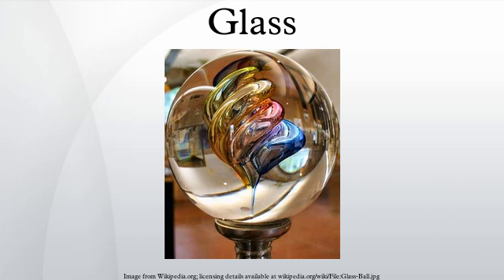The reason for the observation is that in the past, when panes of glass were commonly made by glass blowers, the technique used was to spin molten glass so as to create a round, mostly flat and even plate. This plate was then cut to fit a window. The pieces were not, however, absolutely flat. The edges of the disc became a different thickness as the glass spun. When installed in a window frame, the glass would be placed with a thicker side down both for the sake of stability and to prevent water accumulating in the lead cames at the bottom of the window. Occasionally such glass has been found thinner side down or thicker on either side of the window's edge.